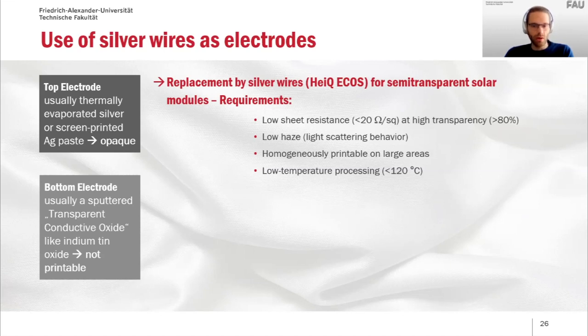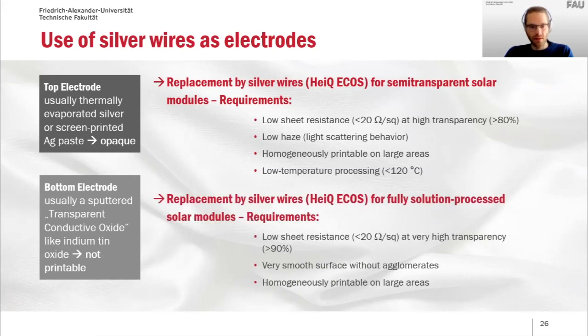And obviously we need homogeneous coatings because the modules have to have a nice appearance. And for roll-to-roll printing, especially with the organic active materials underneath, we need a low temperature processing condition because the materials are sensitive to high temperatures. So we need to stay below 120 degrees. If we want to replace the bottom electrode with silver nanowires, the requirements are similar. We also need a low sheet resistance, but this time we need a very high transparency because this layer is in between the sun and the actual solar cell.